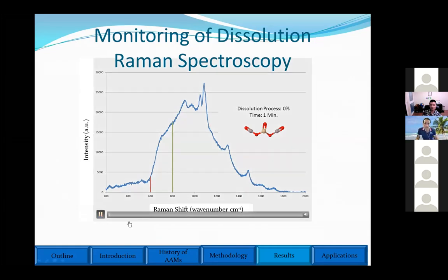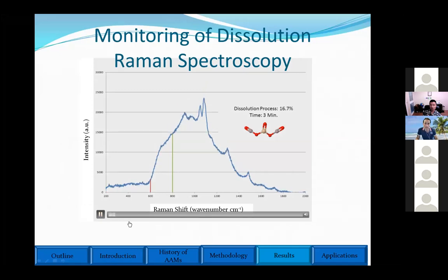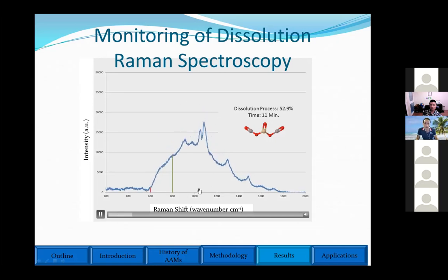And then I got something like this. As you can see here, because the concentration of the chemicals was very high in this example, all the crystalline peaks and amorphous phases of this powder are going down. It means that they are dissolving.